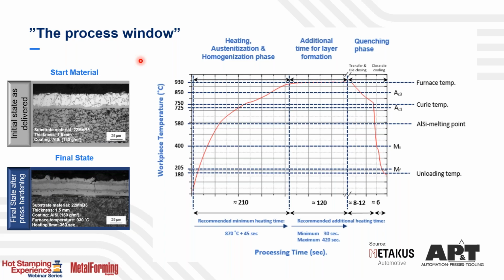After these 45 seconds, we have a dwell time window of a minimum 30 seconds. So actually you need to add from 870, you add 45 seconds, and then a maximum of 420 seconds. That is your process window, where you can still reach the right properties in your final coating, which is in relation to total coating thickness in the final state, and also the thickness of the interdiffusion layer. And since this presentation will be sent out, I think this should be one of these standards for defining or setting up the heating process in press hardening lines.